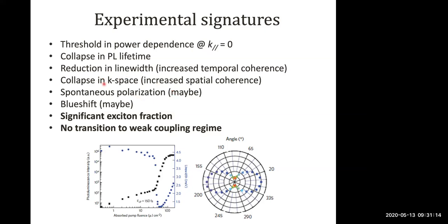We can have, in some cases, spontaneous polarization. This is shown here for a specific material called TDAF. Below threshold, emission is completely unpolarized. When we cross threshold, we have polarization along the pump polarization direction. Here's that threshold in the power dependence, and the reduction in line width.